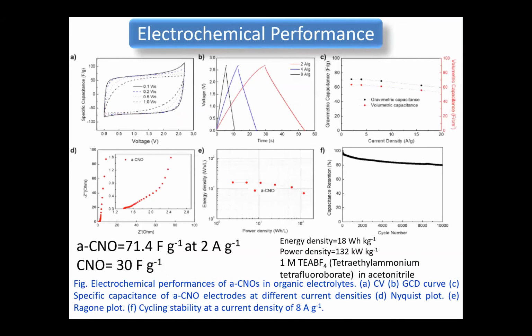Further, the synthesized material has been utilized for electrochemical application, that is, supercapacitor application. Here we have utilized 1 molar organic electrolyte, TEABF4, tetraethylammonium tetrafluoroborate, in acetonitrile. We studied a two-electrode assembly, where we found that activated carbon nano-onions show a specific capacitance of 71 farad per gram at a current density of 2 ampere per gram, while it is 30 farad per gram in the case of carbon nano-onions.